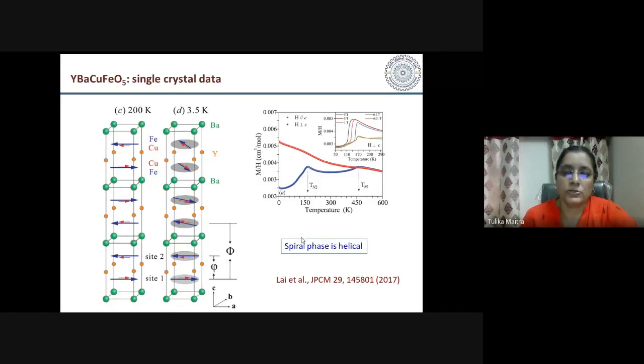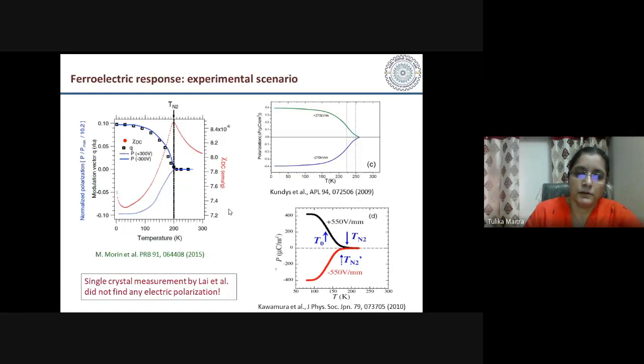And they also didn't find any ferroelectric response in this incommensurate phase. So these two experiments actually contradict each other. One says that in the polycrystalline sample, they see that the spiral phase is cycloidal and there is ferroelectricity, whereas in the single crystal measurement, what they find is that the spiral phase is helical and there is no ferroelectricity. So how to resolve this issue? Okay, so single crystal measurement didn't find any electric polarization, whereas the polycrystalline sample measured not only by Morin et al, but there are other people also who found that there is a finite polarization.